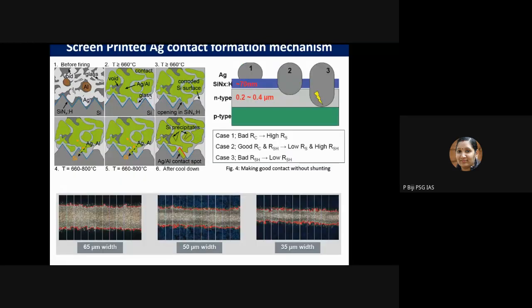Now this is what I told, the silver or aluminium. If aluminium is present, some amount of aluminium also will be present, and the glass material will be there. So they will form some kind of a bimetallic species, and they start to etch out this silicon nitride at its contact, and through that opening, it will be in direct contact with the emitter.